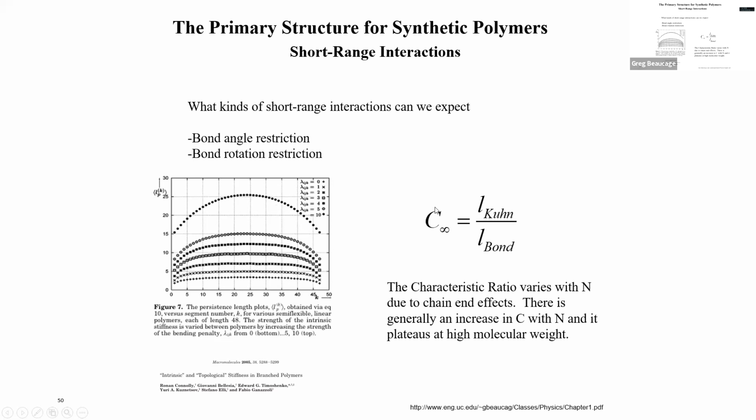Right, so there's some ambiguity about this number in that you can't buy an infinite molecular weight chain, or you might have polydisperse samples, right? So basically there is a little bit of ambiguity from a fundamental perspective. There's an actual number, C infinity. And you can look at different molecular weights and extrapolate to C infinity if you wanted, right? So there is a way to measure. It's not empirical, I think. That's the deal.